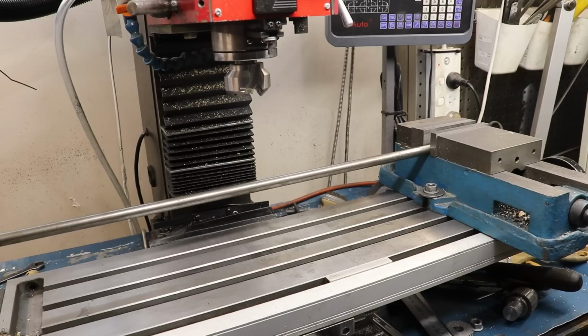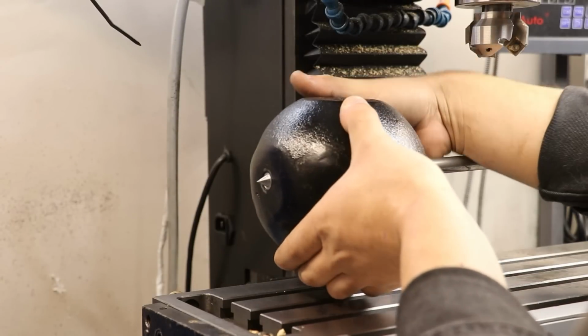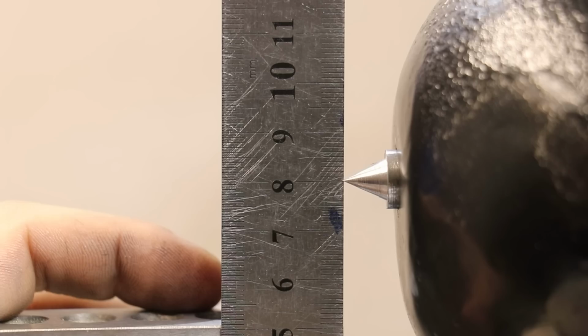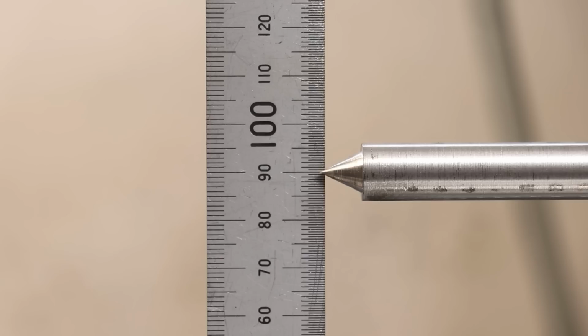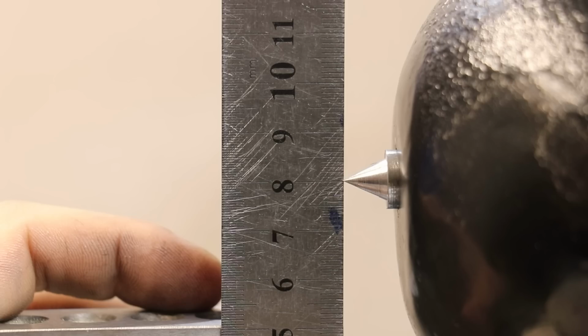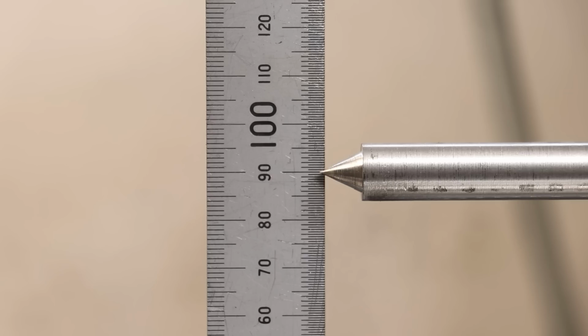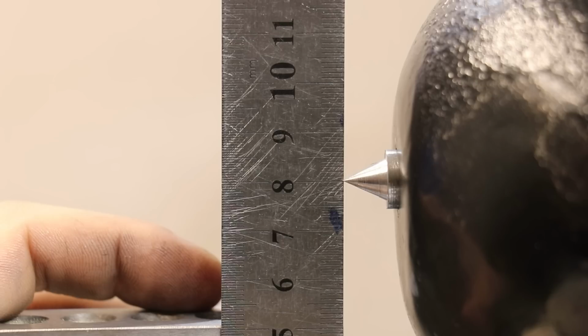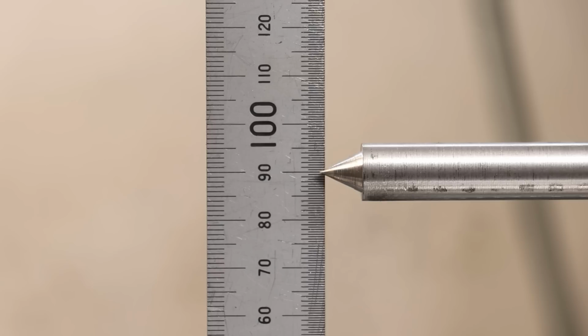Now last week I did a very simple bend test. Not the most perfect example, but I hope I got the point across. If you didn't see it, a long rod was put in the vise and a 9 kilo weight was placed at the end. Over a distance of about 45 centimeters, the end sagged about 10 millimeters, which means that it takes about 900 grams to flex it 1 millimeter. And within the elastic range, you would expect that to stay the same.